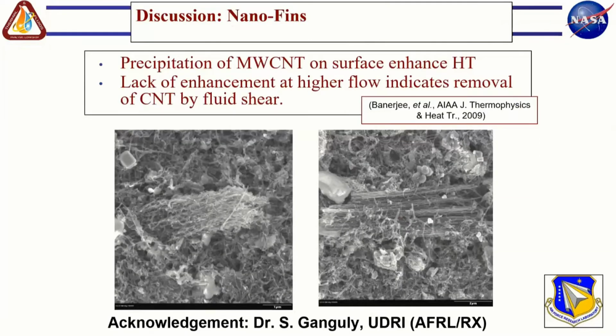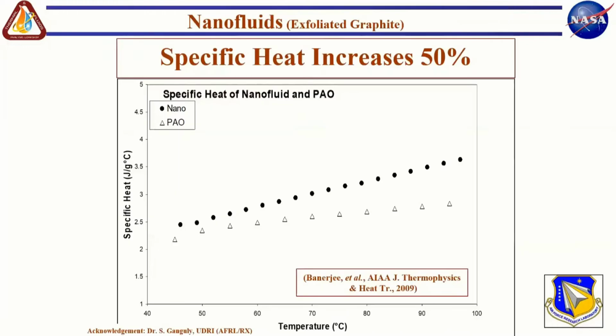And we did it with carbon nanotubes as well. And you can see these carbon nanotubes precipitated as a bundle and gave you a nanofin at the same time. And again, there was no surprise there. The surprise was when we measured the heat capacity of these mixtures.